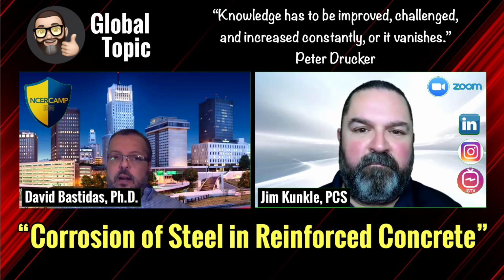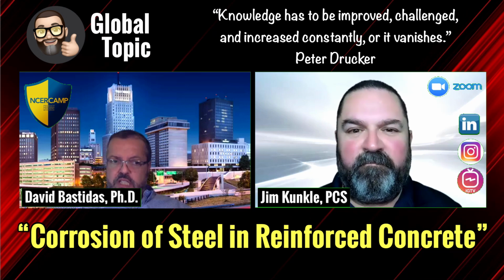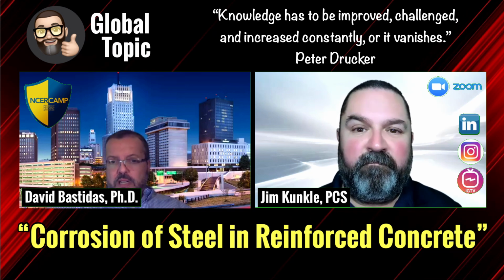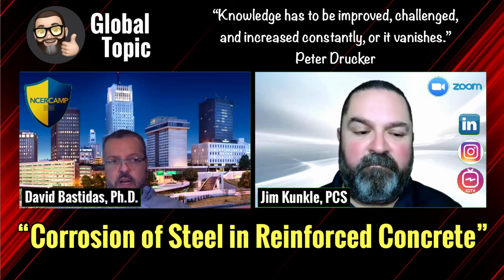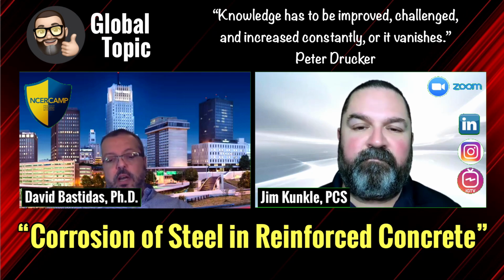The difference is that carbonation ingress from the environment typically follows Fick's first law. This is steady state, and it leads to uniform corrosion. While in the case of chlorides, they are governed by Fick's second law. This is non-steady state, and they lead to what we know as pitting or localized corrosion. Once corrosion starts, there are different stages during the corrosion process: incubation or initiation, and propagation.